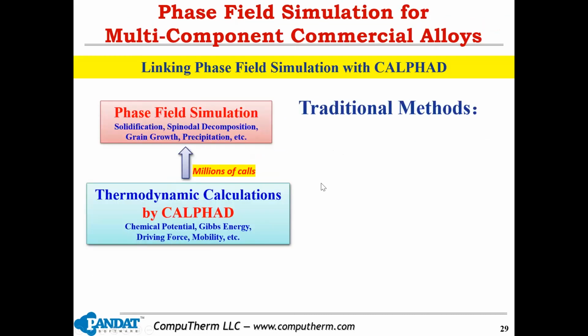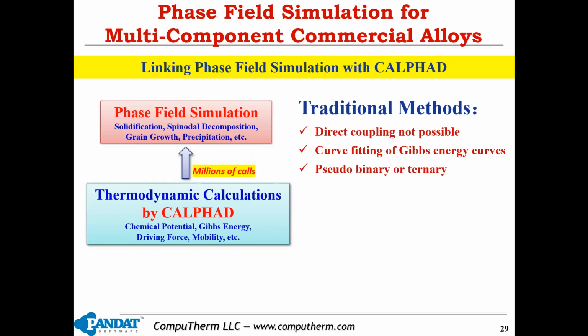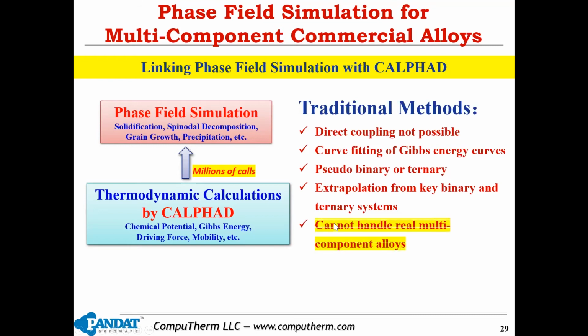So in this situation, in the past, traditional methods usually did phase field simulation by curve fitting of Gibbs energy, pseudo binary and ternary, and extrapolation from key binary and ternary systems and so on, to reduce the simulation requirement. But this cannot really handle the real multi-component alloys, okay?